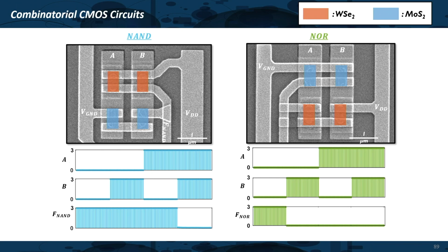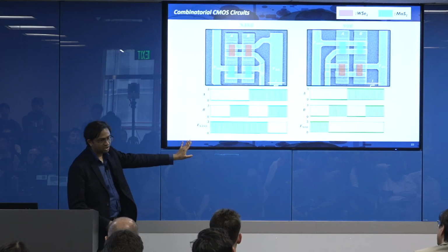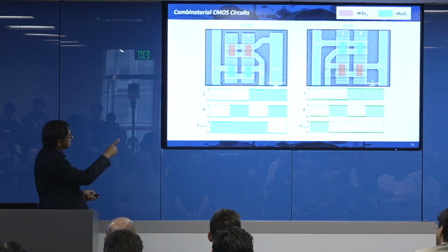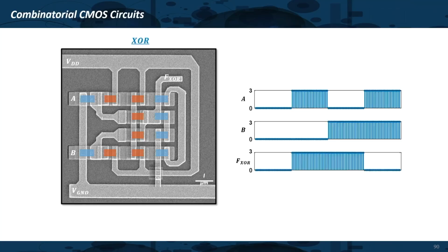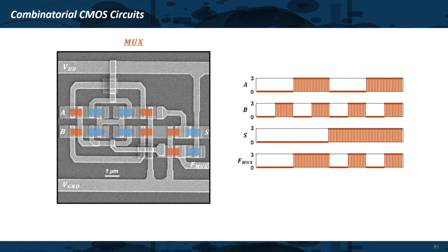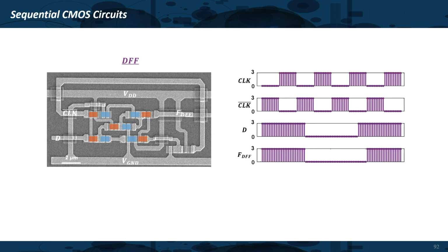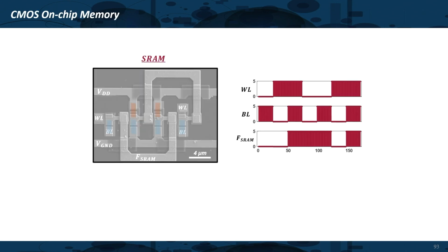right? So you also need to scale the oxide. All the data that I showed you were with EOT numbers of 2.3 nanometer. So we have been using 10 nanometer or 5 nanometer hafnium oxide, and we are able to get down to really low voltage operation of this transistor, and that is why we can now make the circuits operate. So these are NAND and NOR gates, XOR gate, which requires more transistors, multiplexers, D flip-flops, because you do not only need combinatorial circuits, you also need sequential circuits, right, in order to design a computer. So we can make D flip-flops, we can also make SRAMs, right.